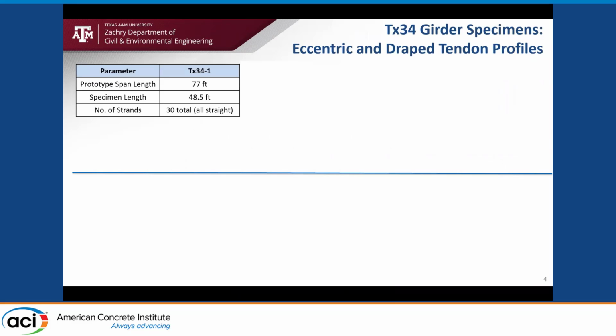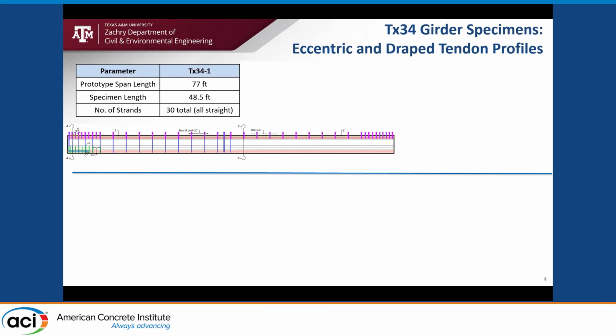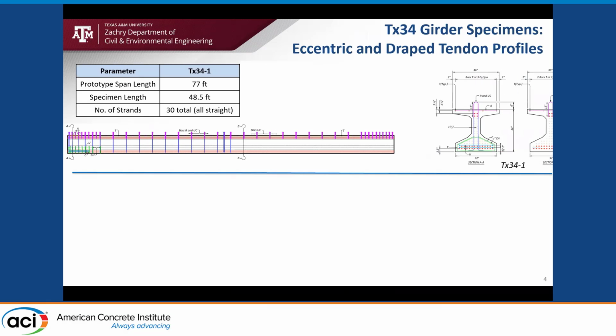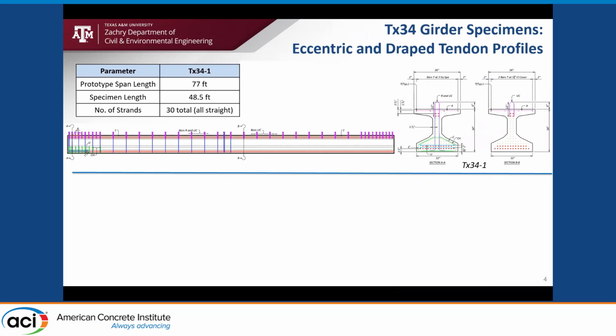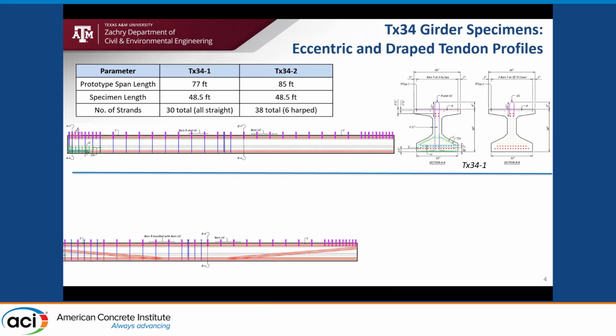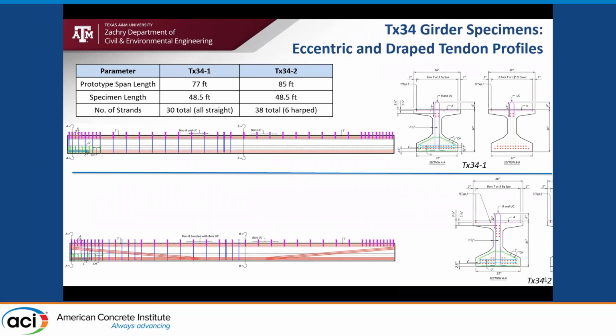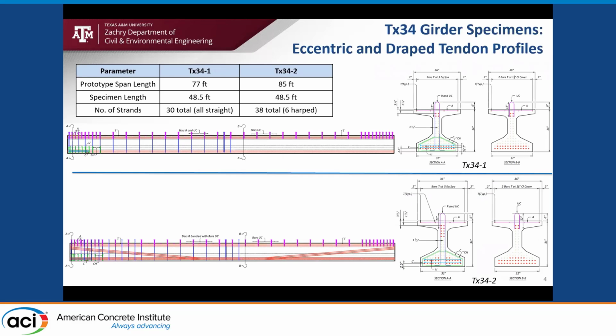We cast two 50-footer long full-scale specimens. The first one was with 30 strands, which were all straight, and we got a prototype design of 77 feet span length with this one. And the second one was with 38 strands, and we had 6 strands harped. And this specimen had a prototype length of 85 feet.